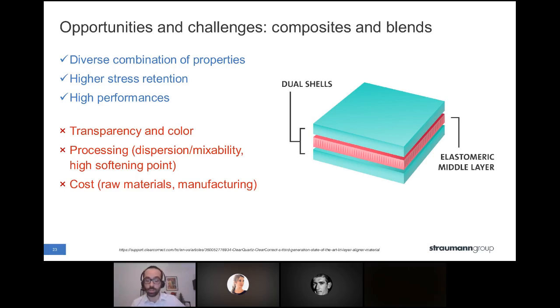I don't exclude composites or even blends. They could achieve the same results, but they have to face a material which is now quite well perceived by the market. It is not too expensive, and it matches all the properties. And in particular, when it comes to composites and blends, I can see these issues or challenges. The transparency and the color can be a problem, especially the transparency. The refractive index of the materials should match very well, and also the intimate adhesion between all the interfaces should be optimal. And the processing could also add some problems, especially could result maybe in higher costs, also associated to the raw materials.